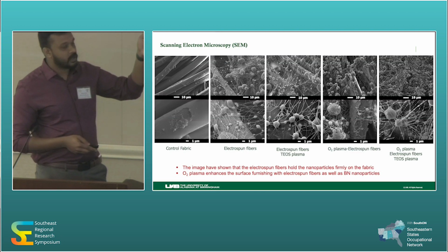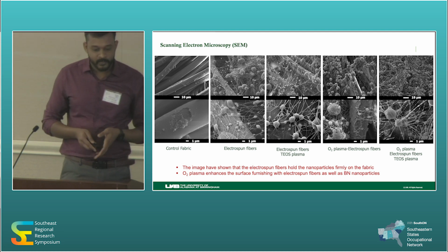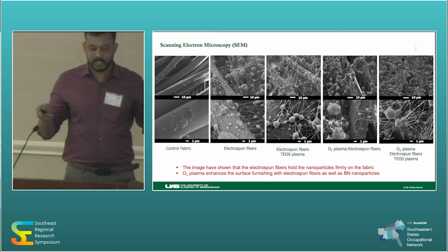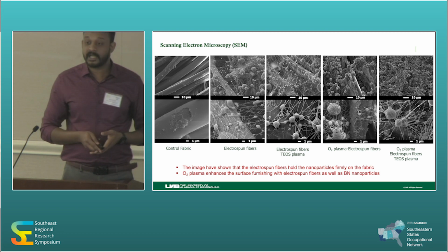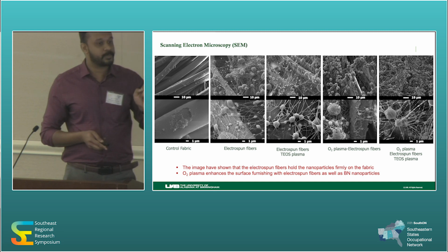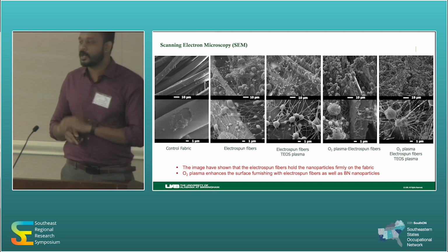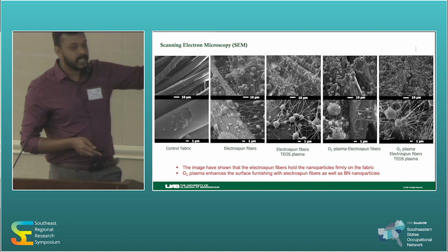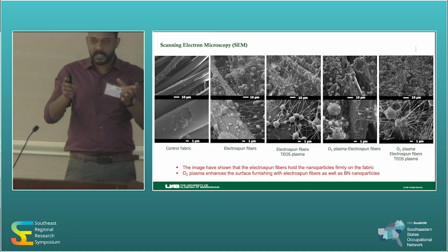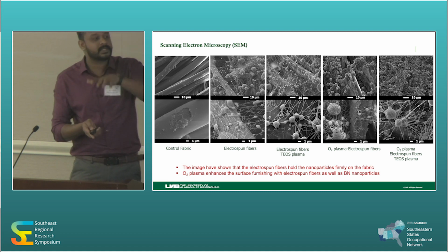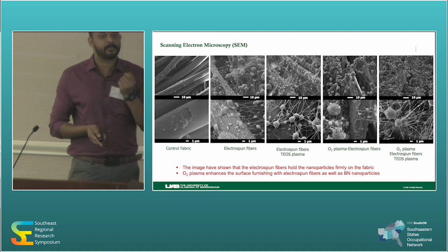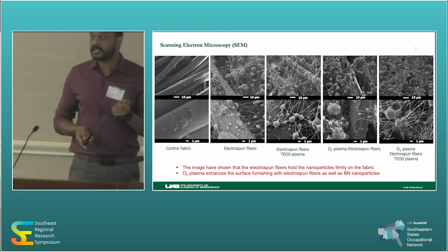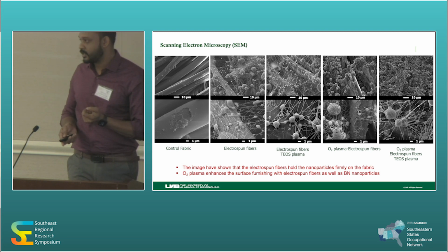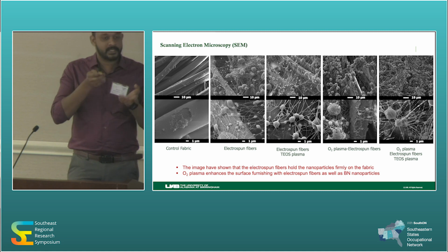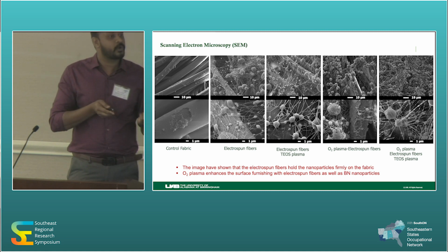This is the SEM image of the entire substrate we have. First one is the control fabric. This is not having any coating, just the control fabric. Then the second one is electrospun fibers on top of the fabric. Electrospun fibers means 5% PET solution with boron nitride nanoparticle. From the image itself, we can see the boron nitride nanoparticles are covered, captured and firmly attached on the fabric fibers with PET. That's why I mentioned PET is acting like a binding agent. So it can ensure that the boron nitride nanoparticle will be there for a long time.